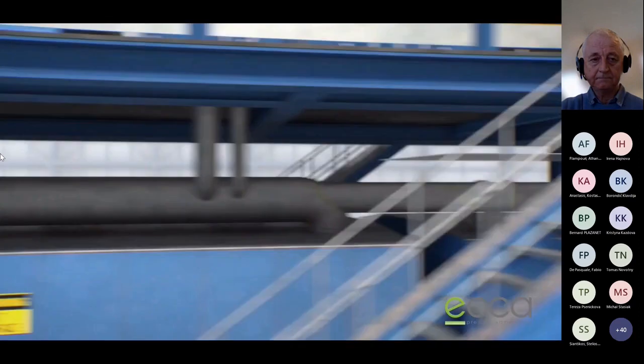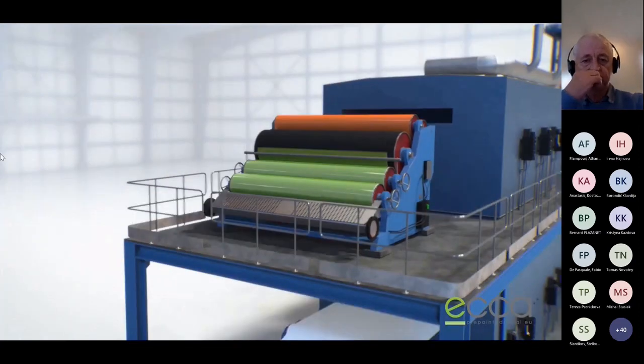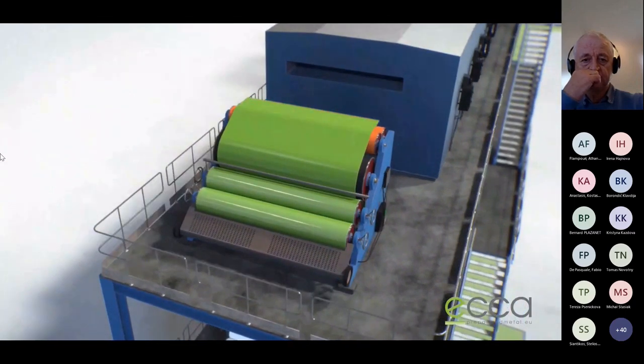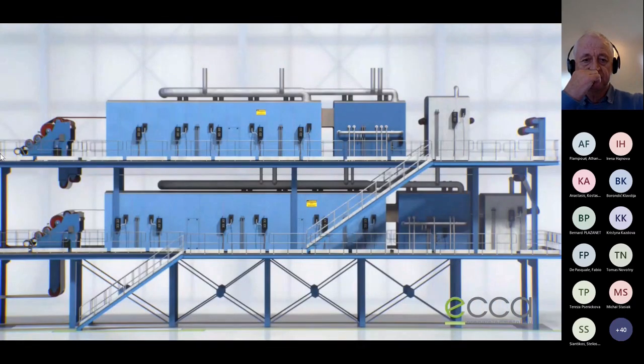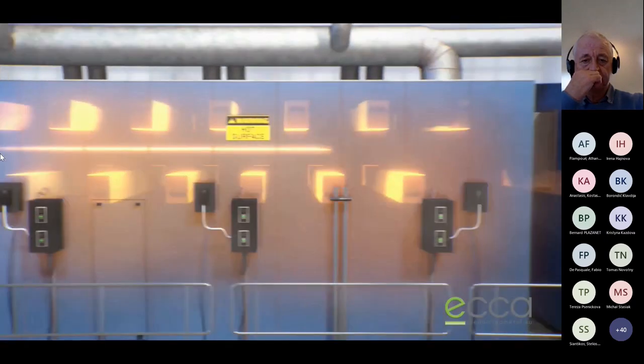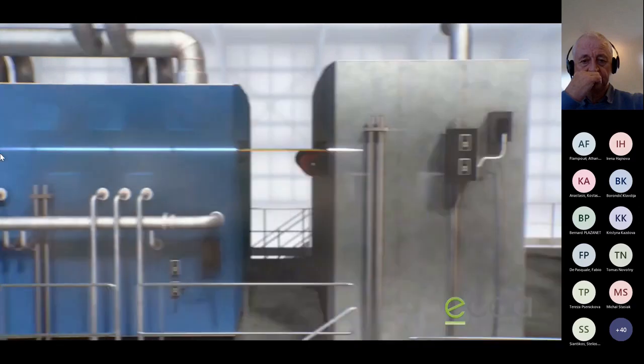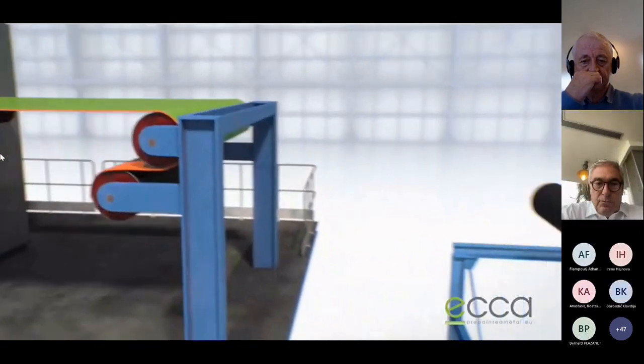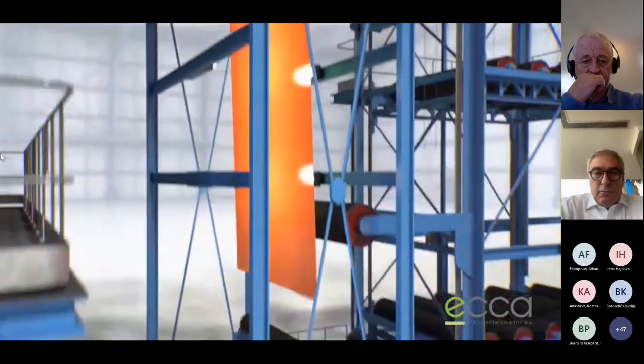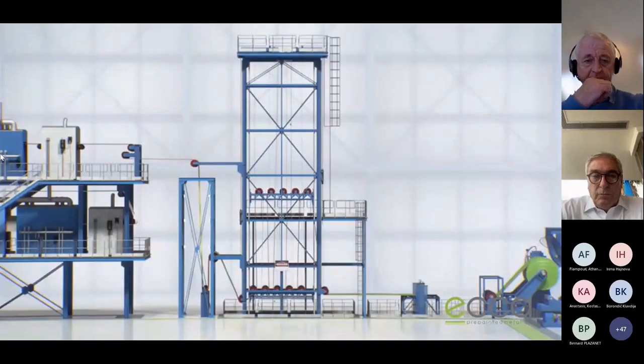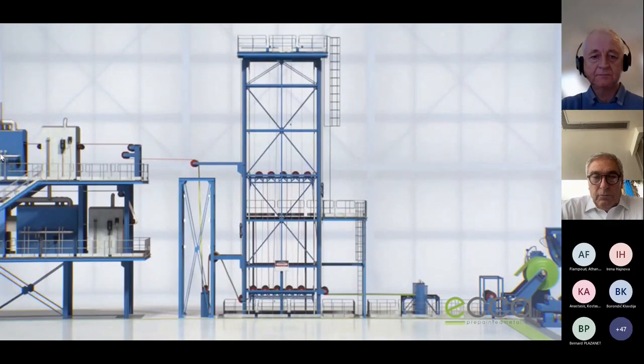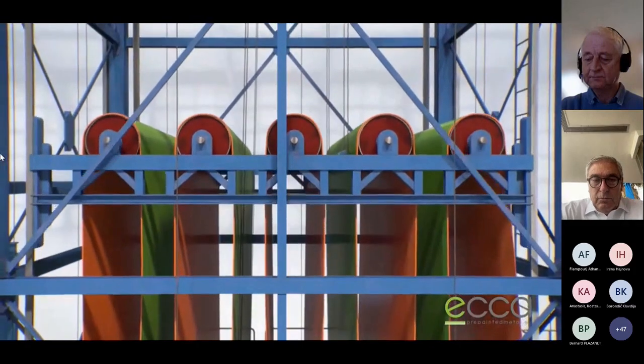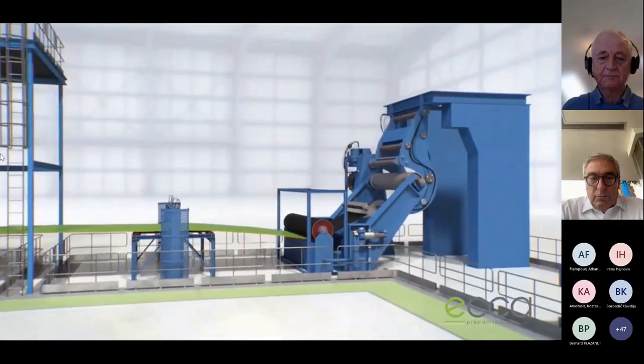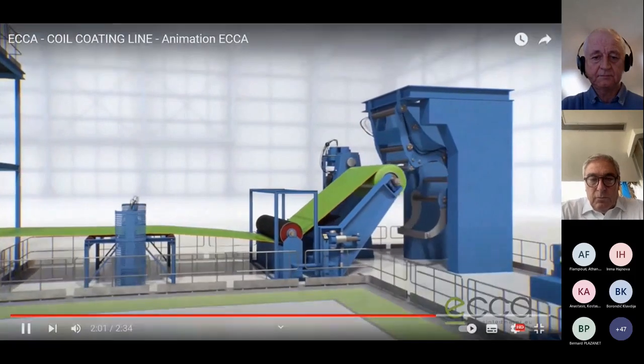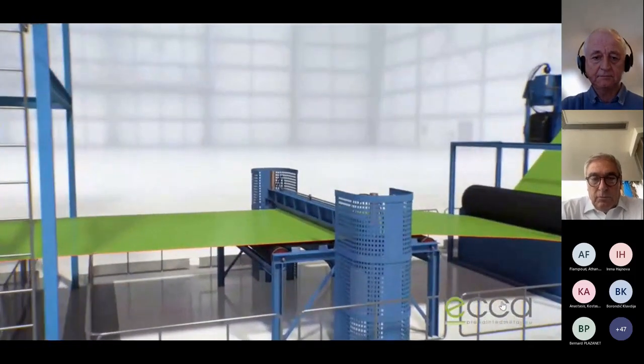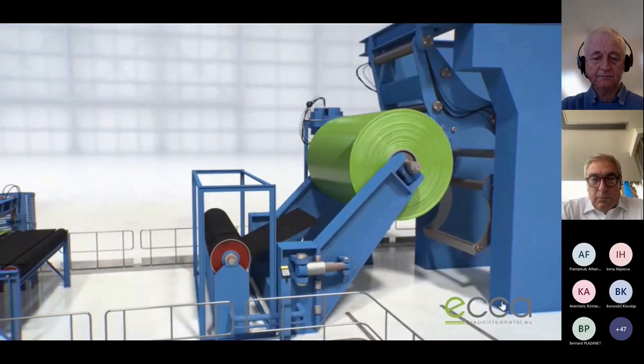The strip then reverses its direction and passes through a paint coater that applies a green top coat, followed by the application of an orange backing coat. From there, both coatings are cured in a second oven, cooled by water quenching and dried as before. The painted coil passes through the illuminated area for quality inspection. The strip then enters the exit accumulator, which under normal running conditions is kept empty. This accumulator allows the line to run continuously by filling up while the exit section slows or stops in order to remove a completed coil.